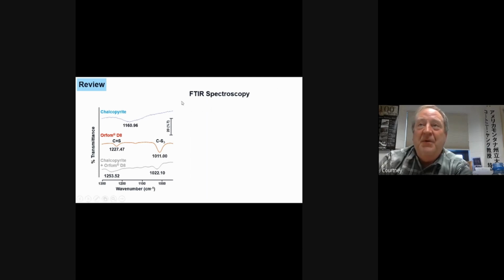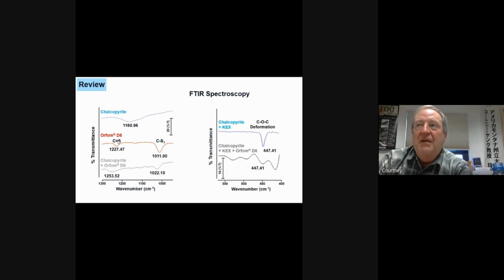Anyways, FTIR spectroscopy, we also used it, and chalcopyrite has a peak of around 1160.96, pure chalcopyrite. Pure Orfom D8, a carbon sulfur double bond is 1227.47 wave numbers. And then the carbon sulfur single bond is about 1011 wave numbers. Both of these bonds change their position to 1253.52 in comparison and 1022.1. So this shift is telling you that the Orfom D8 is reacting with the chalcopyrite through the sulfur functionalities, not through the carbonate functionalities.